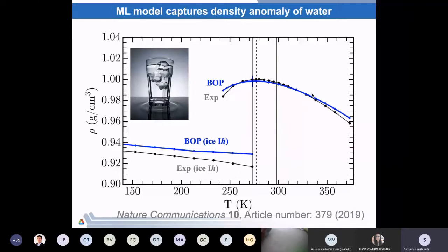So these interactions between the water molecules, both intramolecular and intermolecular interactions, are often very hard to capture for any computational framework. What we did is that by using our framework, we came up with this model called the bond order potential, the one that you see in blue. And for comparison, we have the experimental data shown in black. You can see that this model that we have developed is able to capture all these different features of liquid water and for ice. When you look at the density as a function of temperature, this model captures the features much more accurately than the best models that are available.